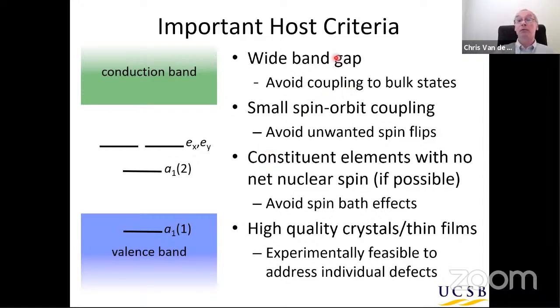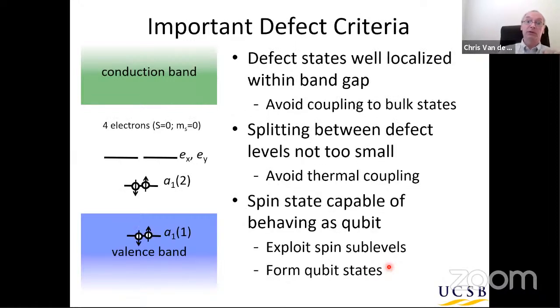You would like to have the host material have a wide band gap, so that the states induced by the defect, as is illustrated here for a vacancy in diamond, are located nicely within the band gap. There is minimal coupling to the valence band or the conduction band. You would like to have a material in which spin-orbit coupling is small, because spin-orbit coupling can give you unwanted spin flips and a loss of coherence. That then relates to the fact that the constituent elements, if possible, should have zero nuclear spin to avoid interactions with nuclear spins that can lead to spin flips. And the material should be able to be grown in high quality in thin films, and be experimentally feasible to create and address individual defects.